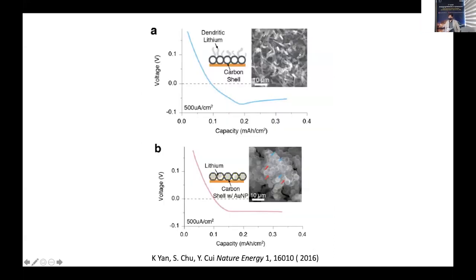So using the seeded hollow carbon at the bottom, after depositing some capacity, you don't see filamental lithium growing out of this hollow carbon. However, for the hollow carbon alone on the top, without the seed right there, you see this filamental lithium structure, the deposition going out. This will get in touch with electrolyte. They're going to react with electrolyte. So the top case will be less stable. The bottom one presents a lot more stability.